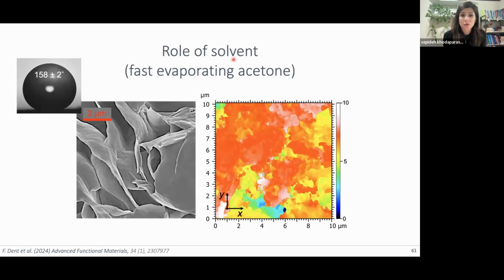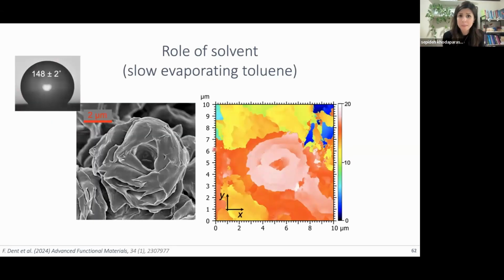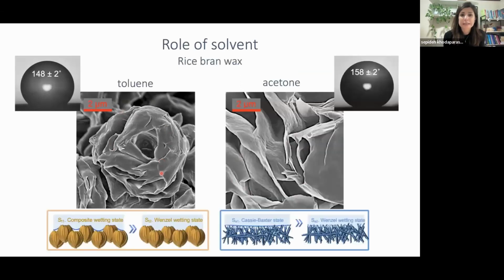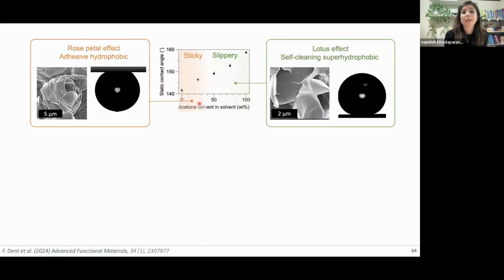If you use solvents that evaporate quite fast and create a large gradient of concentration in the film, you create structures that are really nanoscale pores on the top of the surface, and you create these super hydrophobic surfaces. If you use solvents that have low vapor pressure, and they evaporate slowly, then you create larger structures. These structures will have direct influence on the wetting behavior of these coatings.